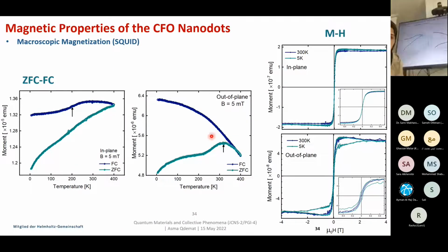For in-plane, we can see in the zero field cooling, the green curve, we have such a maximum here. It comes up due to the addition of the two sublattices of the cobalt ferrite nanodots, which ends up with such a high value, and it occurs at a temperature called the compensation temperature. For out of plane, we could not see any indication of a magnetic interaction, and here we can see the blocking temperature. After that, the particle goes to the superparamagnetic state, where all the particle spins are oriented randomly.